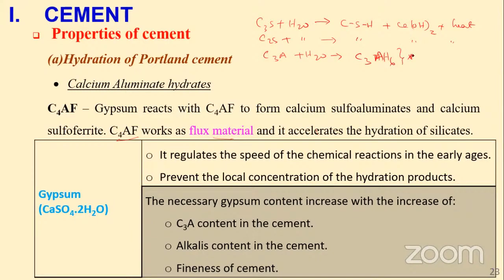But this reaction is extremely exothermic, so we are trying to inhibit that. So tricalcium aluminate in the presence of water and gypsum will form calcium sulfoaluminate. Now this material, when it's formed, coats the particles of tricalcium aluminate, giving time for the particles of tricalcium silicate to react. Then finally, tetracalcium aluminoferrite reacts with water to form, of course, calcium sulfoaluminate. So you can write your equations in this form instead of writing them in full.